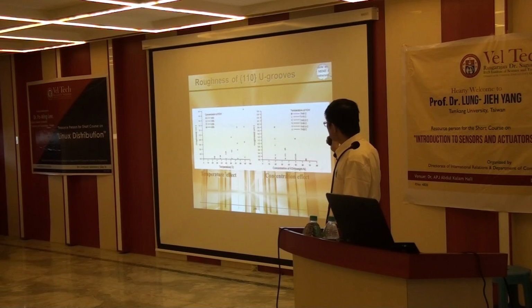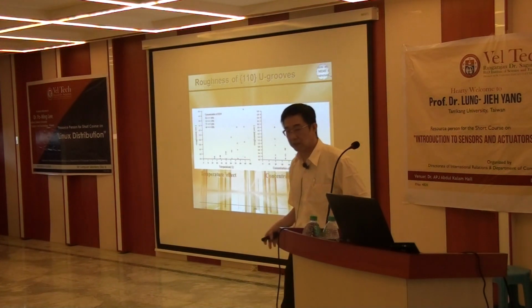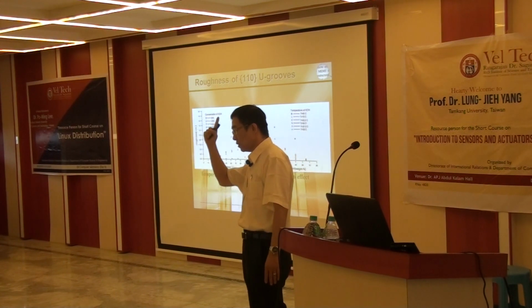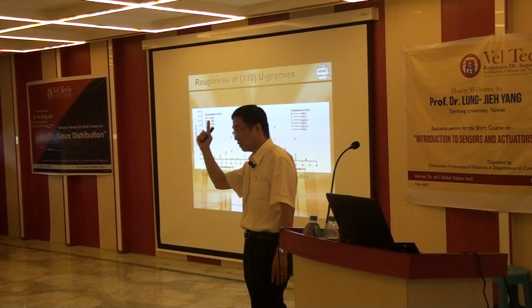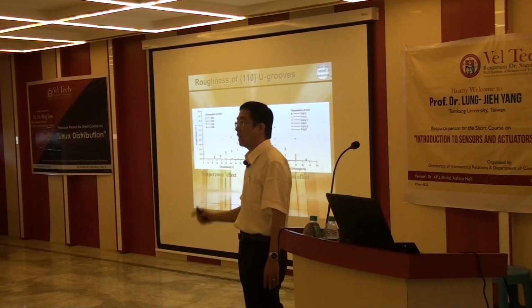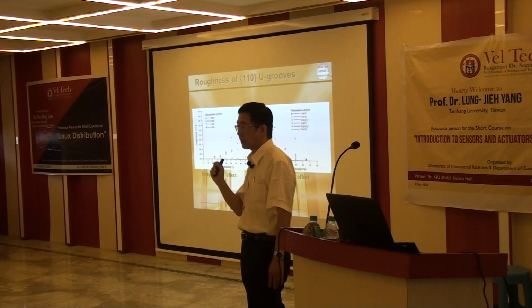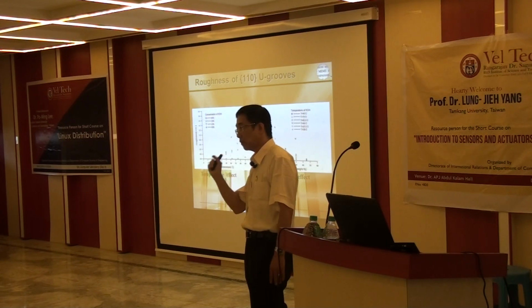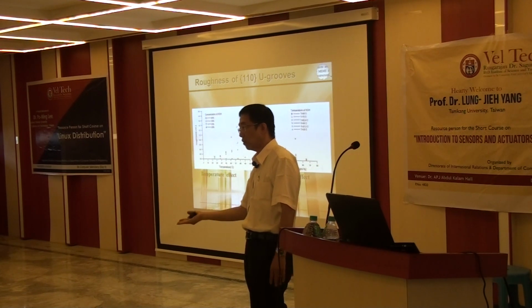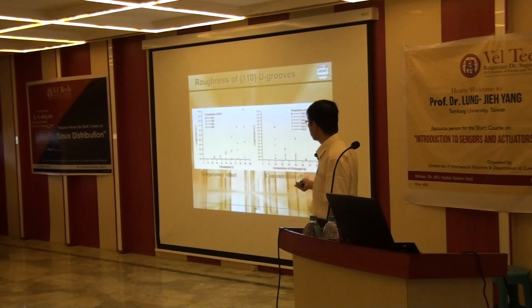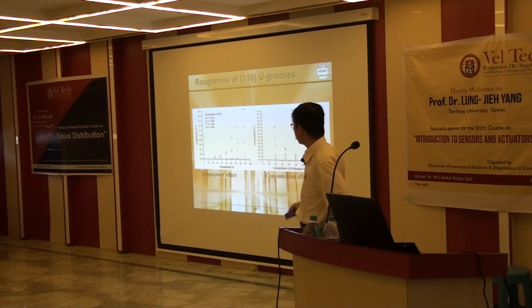Roughly, I want to talk about the recipe: try to optimize your recipe, and try to reduce the roughness value as small as possible. Basically, the etching rate of the silicon gets less as you increase the concentration. Yesterday I mentioned, increase the concentration and the etching rate goes down, and roughness also gets better. So sometimes we try to increase the concentration somewhat. Don't let the concentration be too low, for our roughness. Roughness is also very important for our MEMS device.